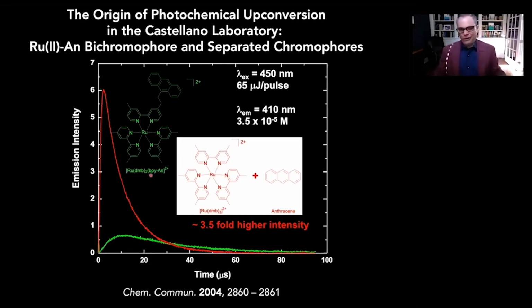If you looked at the cuvette, you saw blue fluorescence. It was really obvious. So we decided, let's turn our detector backwards and see what it looks like in a time-resolved experiment. And this is what you had seen, a clear signature of delayed fluorescence from this molecule. And then we recognized, oh, what we're probably doing is making two triplets on two different molecules. They're annihilating and generating the singlet fluorescence you see.